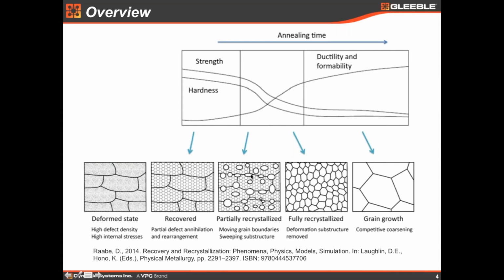and then you can see a deep decay of the mechanical properties and an increase of ductility and formability. So after the end of the process, we have the fully recrystallized microstructure full of grains and a very low density of dislocations as opposed to this initial state. So you have a big decay in strength and hardness, and an increase in ductility. After that, if you keep the metal at temperature, the grain will grow. So this is basically an overview to summarize the whole process.